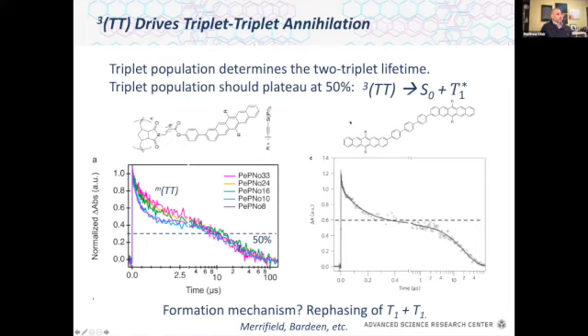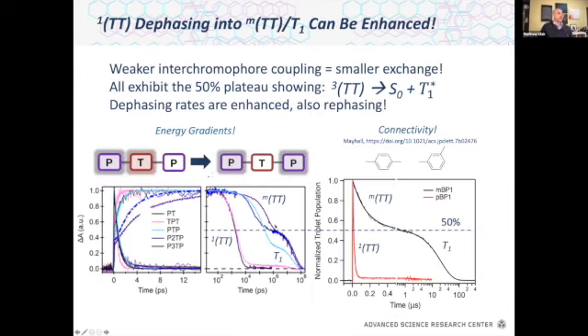This is a polymer in a completely different structure. This backbone extends. This is a non-conjugated backbone, and we have these dangling singlet fission chromophores off. Oops, I put the dash in the wrong place, but the 50% line is here. Again, we get to the 50% plateau. We can change the connectivity. There's a nice theory paper showing how this works and gets to our 50% plateau without even changing the proximity, just changing the bonding. And then we can see 50% plateaus in custom design systems where we put energy gradients in to spatially separate the triplet pairs. So they start close to each other and then progress to a more spatially separated state.